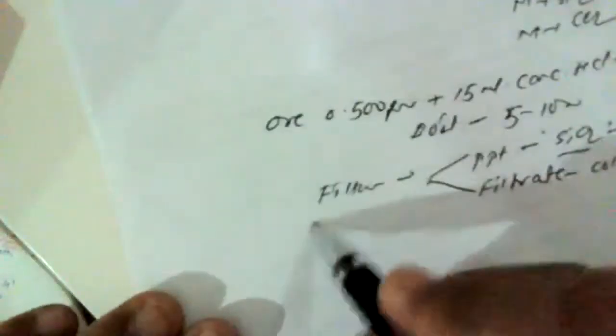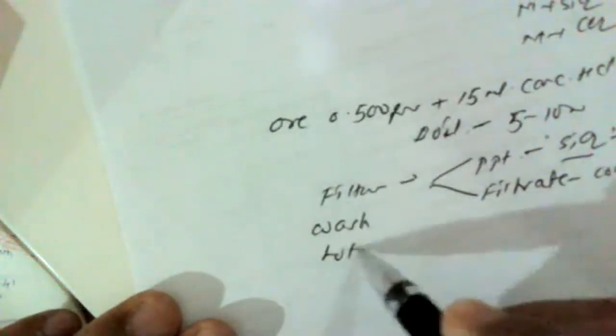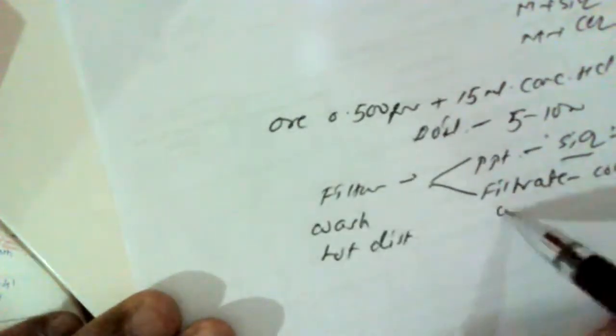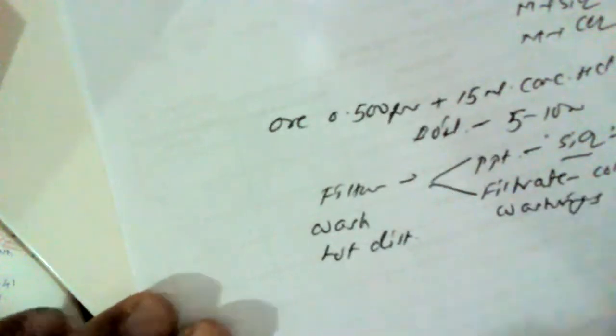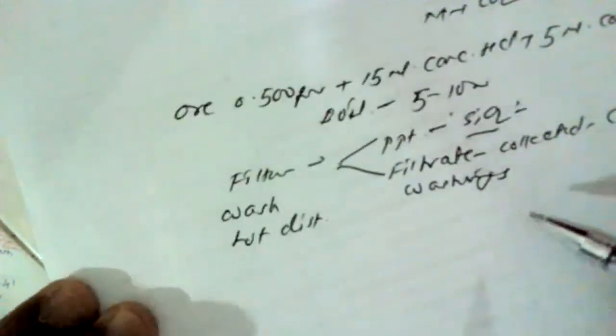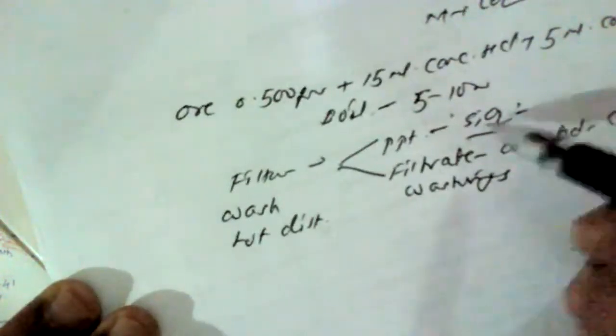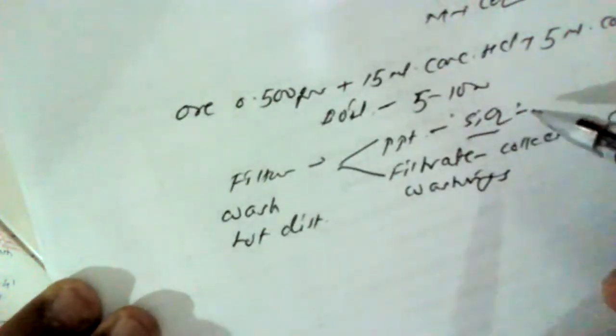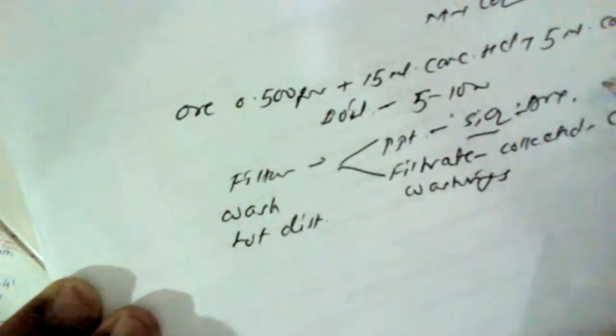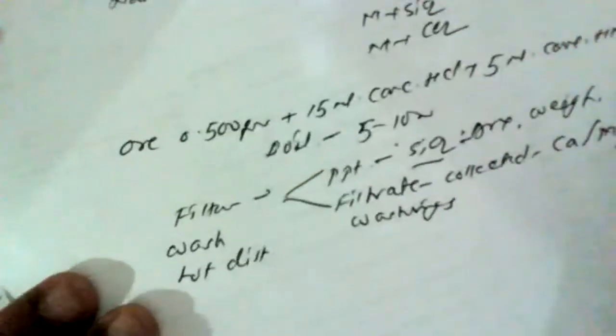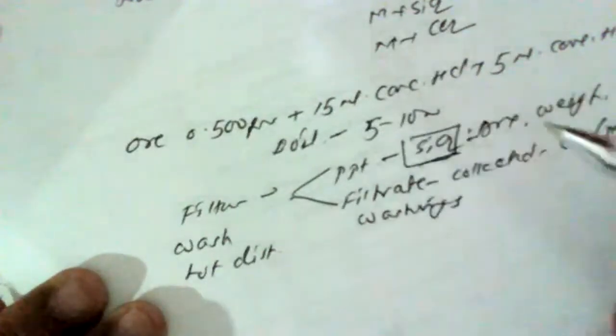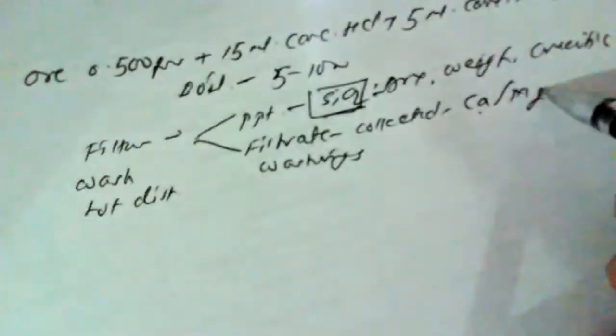After filtration, we have to wash with hot distilled water, and we have to collect the filtrate and washings in a separate receiver. By following the usual procedure, we can dry this filter paper, and we have to weigh it by igniting it in the previously weighed crucible. So this is how we can determine the content of silica. Now our aim is to determine the calcium and magnesium content.